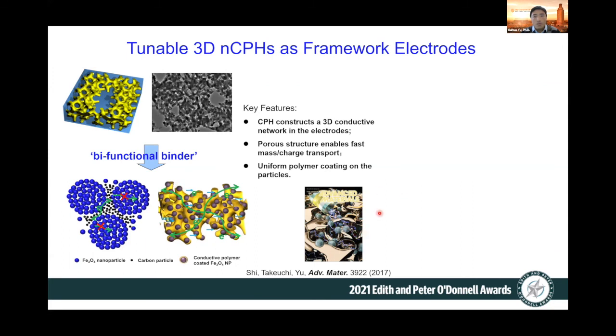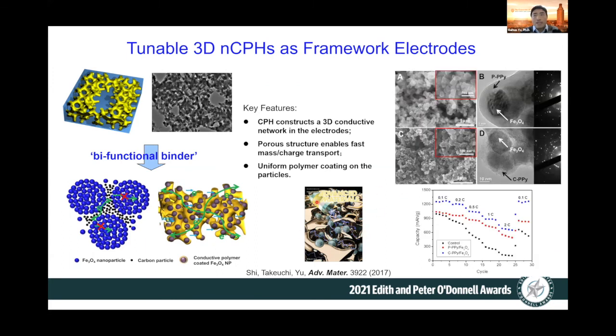And so we use this as one example. We make this magnetite, which is Fe3O4. It's very abundant in nature, and it has a theoretical capacity 3 times as high as the current commercial graphite anodes. But it is electrochemically very sluggish due to the very tedious process of intercalation, conversion, and then reconversion. So it's very challenging to make this material work. So we demonstrated this gel, the Fe3O4 magnetite particle, with a layer of polymer coating and well separation between the particles.